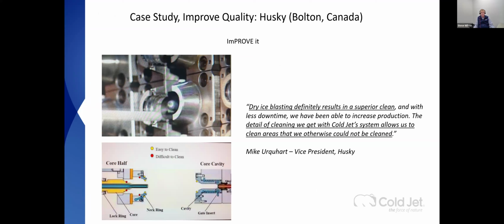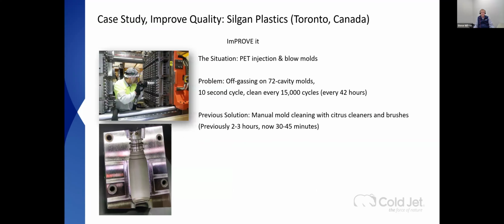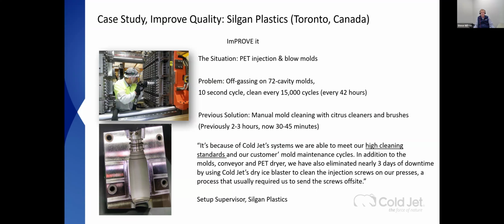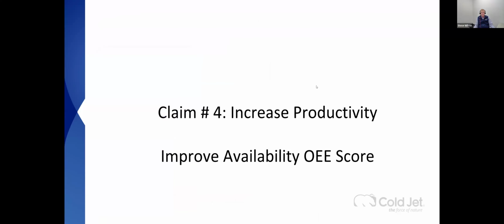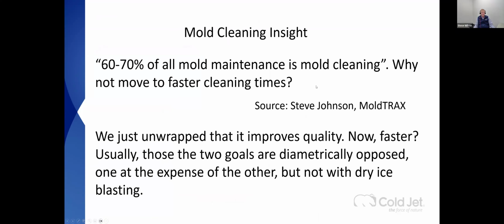It definitely affects the results in superior clean. That's what Husky tells us. That's a preform mold, some very complex geometries to clean. Once again, this is Silgan PET molds, complex geometries. They went from 2 to 3 hours in cleaning time down to 30 minutes, and it gives them the ability to meet the high cleaning standards their customers demand in a preform. That's improved cleaning quality. It increases productivity. Notice 60 to 70% of all mold maintenance is cleaning, according to Steve Johnson at MoldTRAX. Why not do it faster?